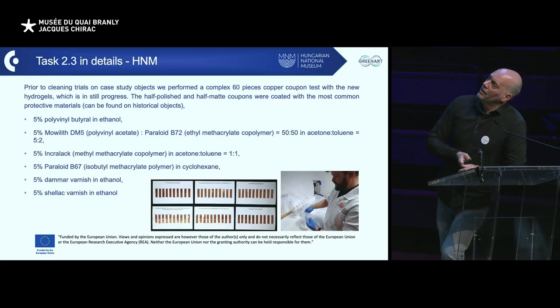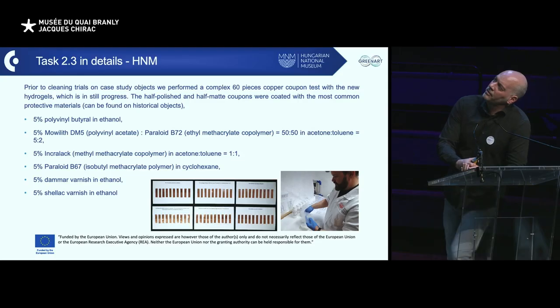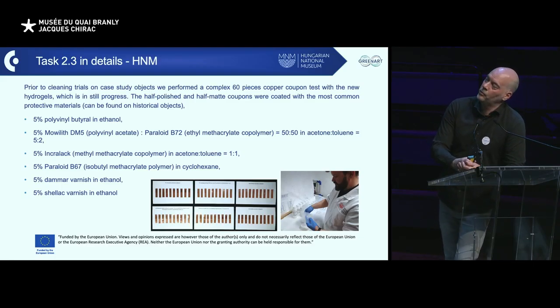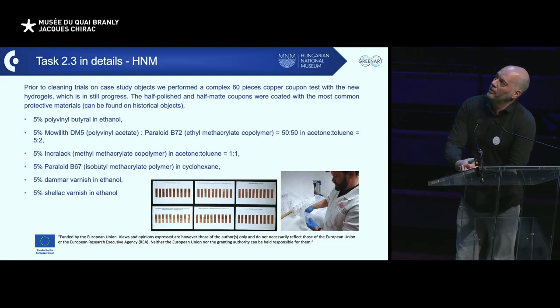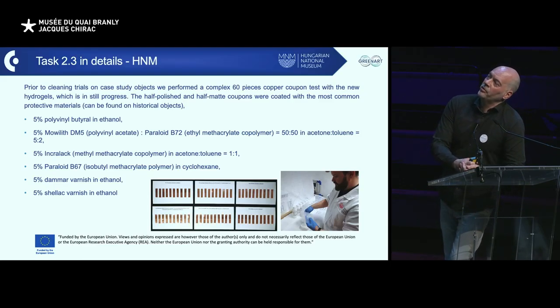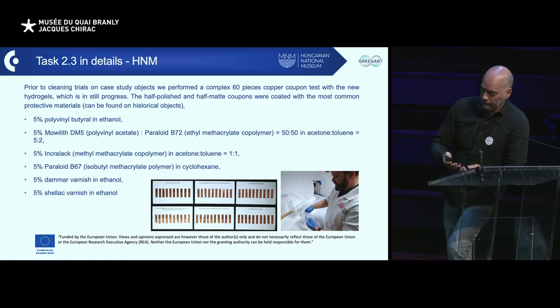And prior to cleaning trials on the case study objects, we performed 60 pieces of copper coupon test with the new hydrogels, which is still in progress. These are half matte and half polished coupons, and we applied onto them the most common coatings we can find on our objects from the storage. They are modern and also historical coatings, as you can see. So we used polyvinyl butyral, Mowilith DM5, Paraloid B72, Incralac, and B67, and also Damar varnish and shellac varnish.